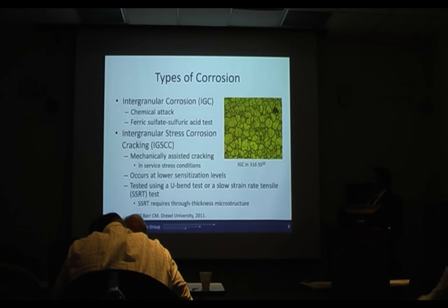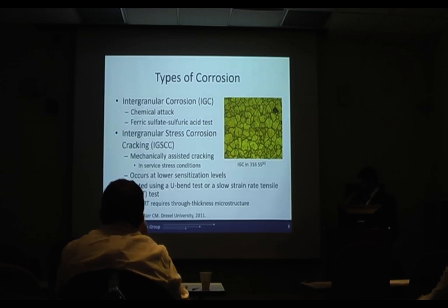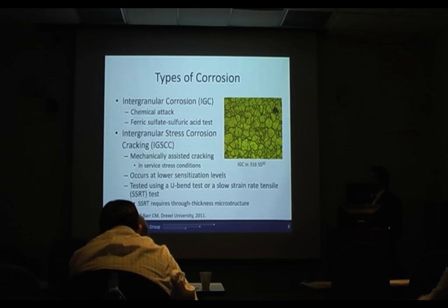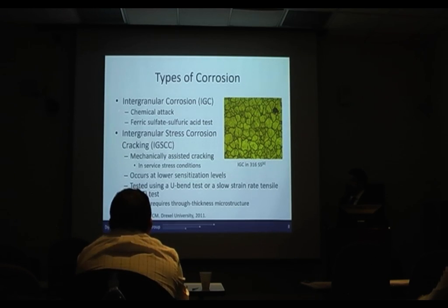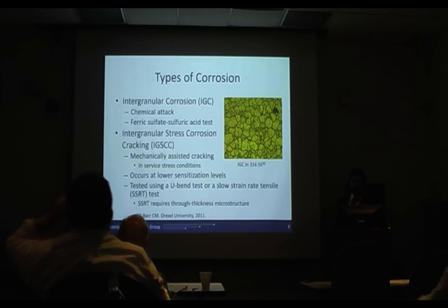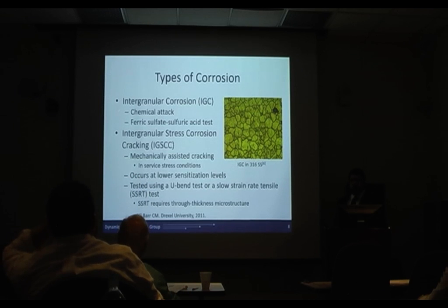However, you also have a second kind of attack called intergranular stress corrosion cracking. And this, in addition to the chemical component, has a mechanical component as well. And it's experienced more in service conditions. And the big thing with this is you can actually get it at lower sensitization levels than you can get the intergranular corrosion. And this is typically studied with a U-bend test or a slow strain rate tensile. And the catch with this is, especially with the slow strain rate tensile, you need a through thickness microstructure to study it because it's machined from the bulk alloy.